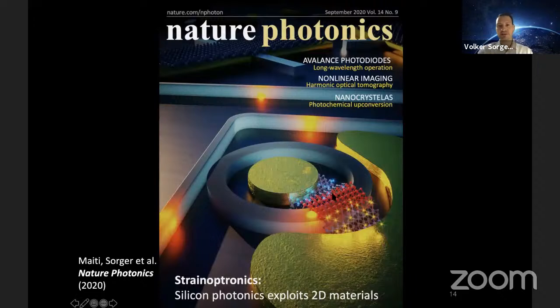So this was a paper we published last year, where we take a light signal and couple it to a photonic ring, and notice here that the 2D material is wrapped around, bent. This introduces strain, and now you see here we have these blue and yellow carriers, meaning we can separate the charges, electrons from holes, and we have photocurrent collecting the charges from here and from here. Notice here in the back, we have another 2D material on top of a waveguide, but it's flat, not strained, and therefore once we send light through, we do not obtain any light absorption, so it's quote unquote dark.